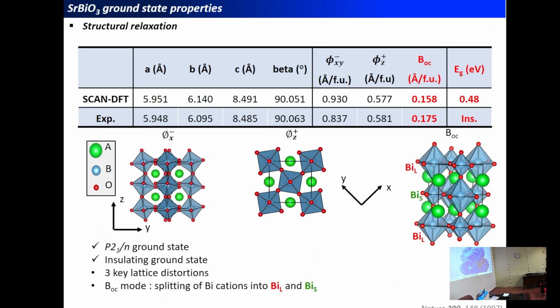So now we can look at the ground state properties of bismutate. I'll focus on strontium bismutate, which was the less studied material. The first thing we have to do with our DFT simulation is the structural relaxation to identify the ground state associated with our parameters. As you can see, with our DFT calculations with the SCAN functional, we reproduce correctly the lattice parameters of the compound. We predict the correct P21/n ground state, which is monoclinic. The material is found insulating with a sizable band gap. The material is found insulating as well in experiment, but there was no real band gap value in the literature, but it is in the range of what is observed in barium bismutate.